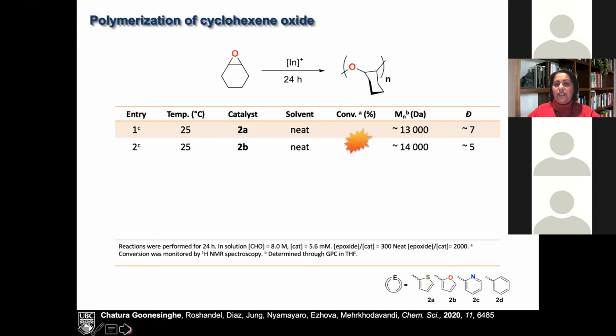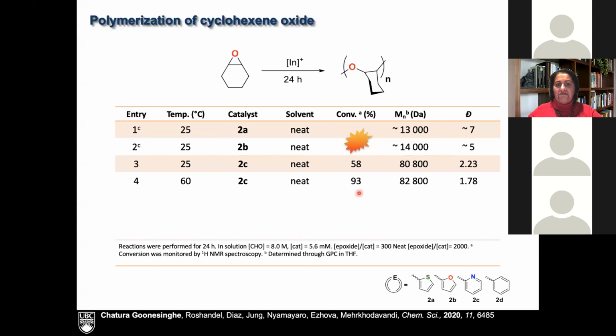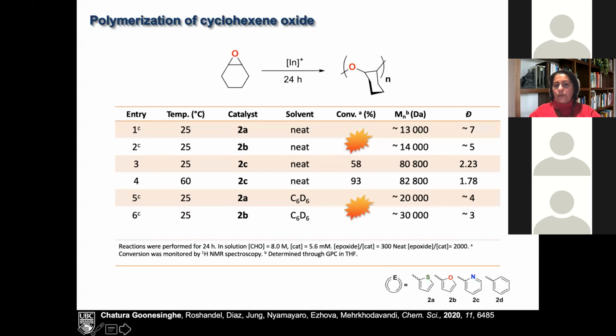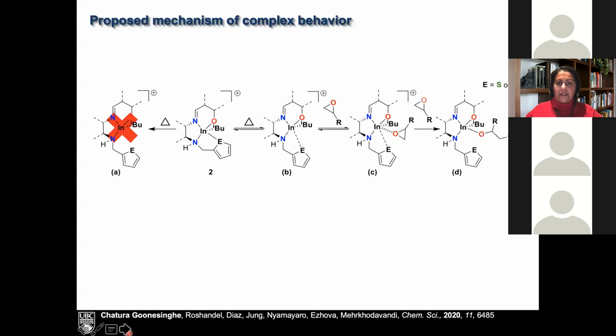So for Chiral, what he showed was that these systems were highly active for epoxide polymerization, explosively so, where the polymer was now all over the glove box, which is not ideal. That was when the donors were sulfur and oxygen, but when the donor was nitrogen, it was a relatively controlled cationic polymerization of epoxide, and that has to do with donor ability, obviously. And this was observed under neat conditions and under somewhat more dilute conditions. Having the strong donor, the pyridine donor, really changed the stability and the reactivity of these compounds.